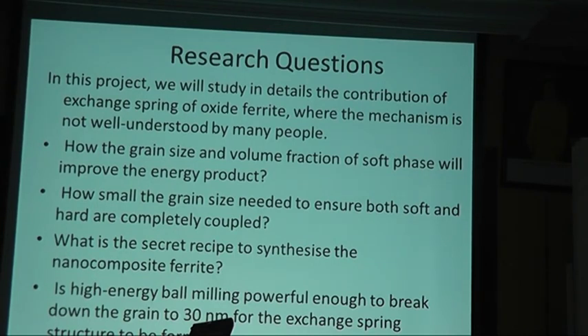But it depends on how many grains you apply. That's for macromagnetic. So actually how small the grain size must be to make sure soft and hard are completely exchange coupled, we don't know. And then what is the secret recipe to synthesize? We're still looking for this. And the last question is very important. Is it possible for high energy ball milling to break the grain down to 30 nanometer for the exchange spring? These questions are very important for the project.